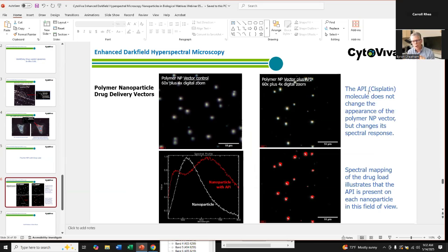In this case, the group is trying to label the polymer nanoparticles on the surface very effectively with the cisplatin. Now, the cisplatin can dramatically change the way that the polymer nanoparticle absorbs and reflects light. And with hyperspectral imaging, we can measure that very effectively. This is the nanoparticle control without the cisplatin, and you can see how dramatically the spectrum of the polymer nanoparticle changes as a result of the cisplatin small molecule drug being located on the surface. And by applying the spectral mapping algorithm, we're able to demonstrate that every polymer particle in this field of view contains cisplatin on the outside of the particle.